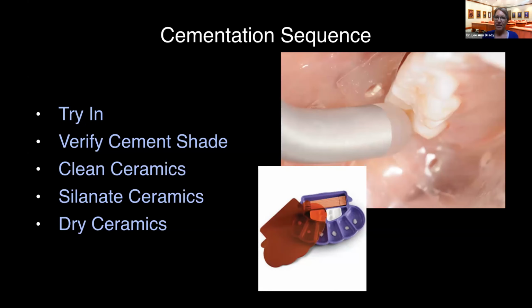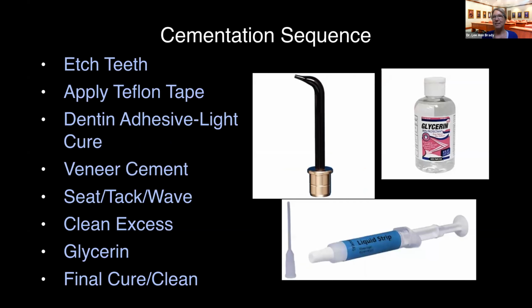Once we've got an aesthetic approval and we've verified what color we're going to use, they come out of the mouth. If they have not been etched by the laboratory, one step, if they're lithium disilicate, feldspar, or leucite reinforced, 60 seconds of Monobond Etch and Prime, rinse and dry, put them in a little ceramic organizer dish. If they've been etched by the laboratory, I'm going to take them out of the mouth, wipe out the try-in paste, and do 30 seconds of Ivoclean, rinse and dry. Then my ceramic primer, thoroughly dry it. You do not light cure ceramic primers. They just have to be thoroughly air dried. And then I'm going to put them in my little ceramic organizer. So that's what I'm going to do to the glass.